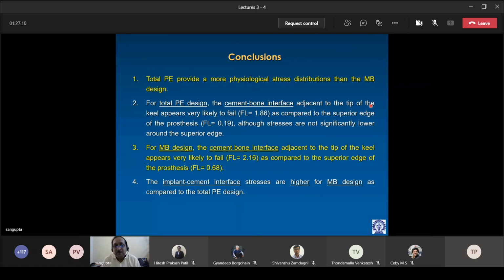Adjacent to the tip of the keel appears very likely to fail. We had calculated the FL value to be 1.86 as compared to the superior edges of the prosthesis. It comes out to be an FL value of 0.19, although the stresses are not significantly lower around the superior edge. This is a very important conclusion.